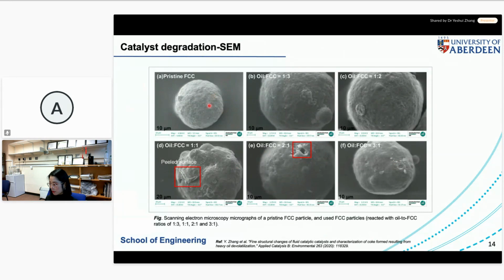We can see the surface of this catalyst particle. In this piece of work I was using a fluid catalytic cracking catalyst, and this type of catalyst is normally used in the oil refinery industry, with particle sizes between 50 and 200 microns. It's rather homogeneous. If you look at the pristine FCC catalyst, it's kind of rough, but at least the shape is quite homogeneous.